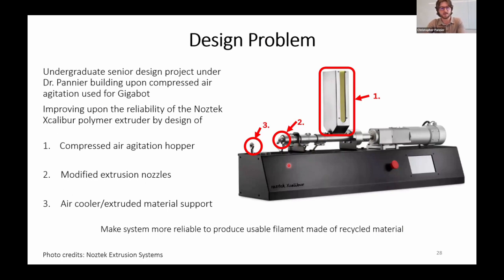It's called the Noztek Xcalibur polymer extruder. We wanted to improve the reliability of the system to make it more possible to produce usable filament made of recycled material. We did this in 3 ways. First, we improved the hopper from the base hopper by developing a compressed air agitation hopper. Second, we made modified extrusion nozzles, at number 2 here, to increase the mass flow rate of material we get out, as well as changing the diameter of the extruded material.